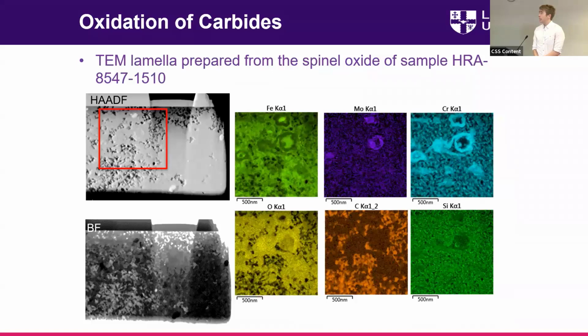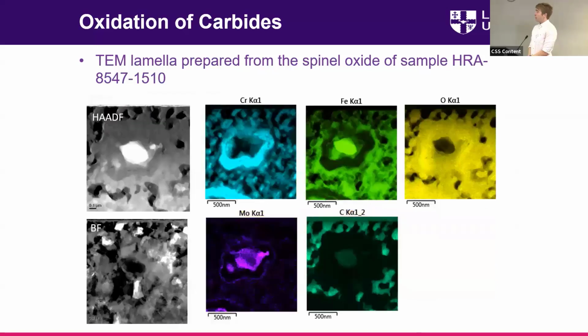So to further look at these, I created a TEM lamella of a sample from the spinel oxide, and we found similar particles in these TEM lamellas. If we have a closer look at this, we can see that there is a chromium-rich oxide ring surrounding an iron-rich core, which hasn't oxidized because there's no oxygen present, and there's molybdenum, which is relatively dispersed throughout this whole area.